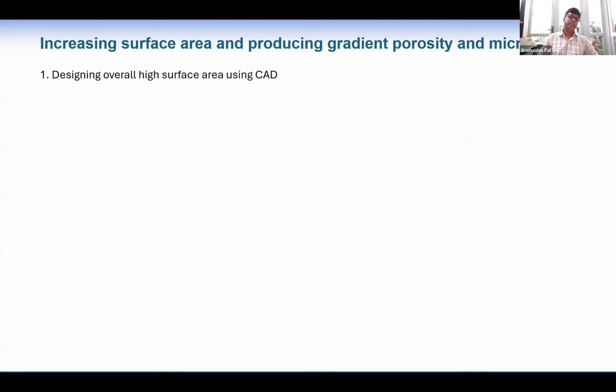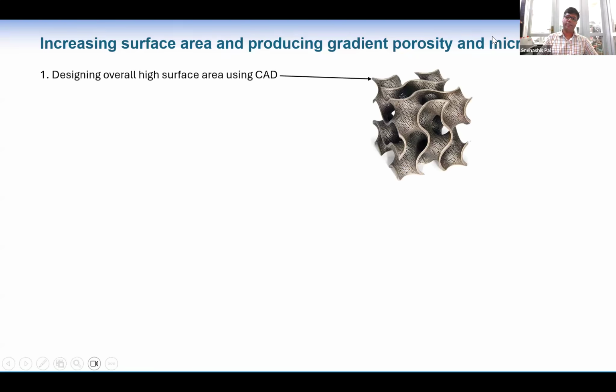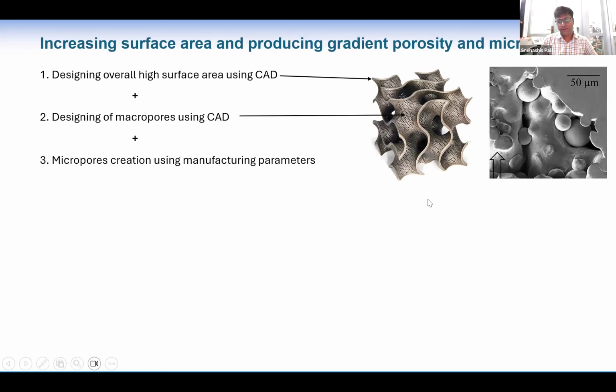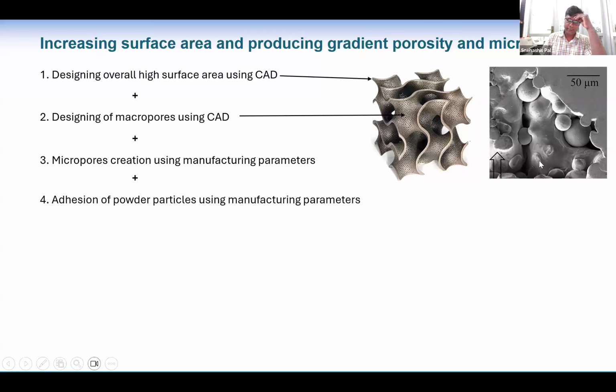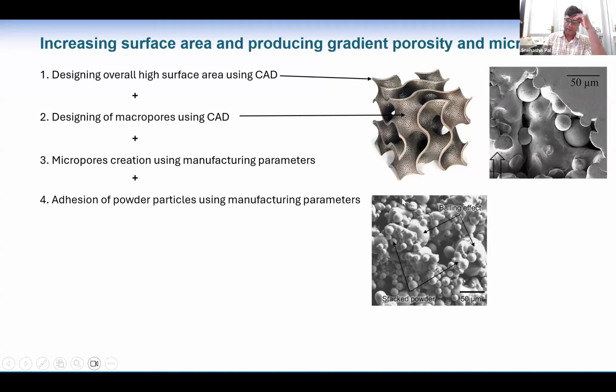For that case, we can increase the surface first of all by the CAD model. Secondly, we can also increase the pores, so that we can increase the surface area, and then by the manufacturing parameters, we can make some pores on the surface, which is another surface area increment. Also, we can increase the powder particle adhesion, so that there will be even more increase of surface area on the surface.